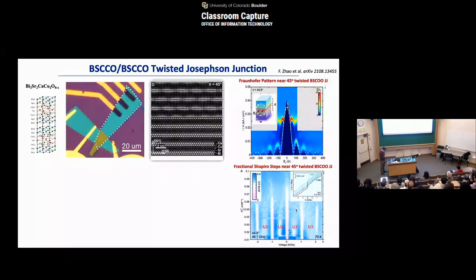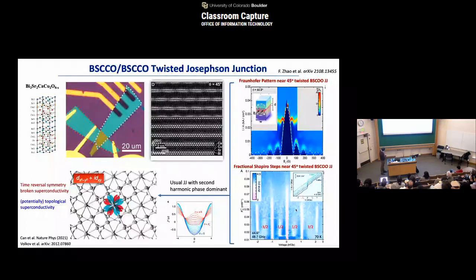Turns out this 45 degrees is very special. If you have the D-wave nature of the wave functions, at 45 degrees you can maximally misalign these two superconducting order parameters. At the interface, you expect to see a d plus id type of superconducting order parameter appear. And as you see, d plus id has the complex conjugate pattern d minus id, which is time reversal symmetry connected.